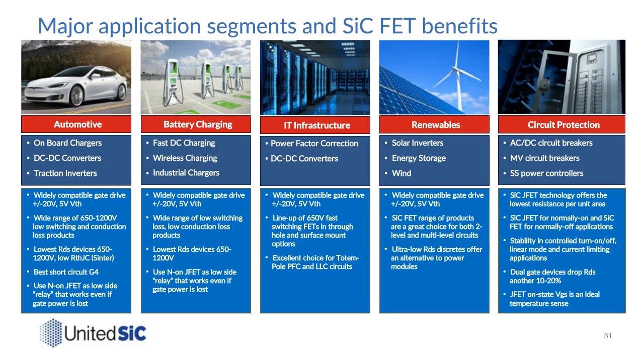This has a 5-volt threshold, so your drive can be 0 to 12, but you can also use other drives if you're looking for compatibility. In liquid-cooled types of applications, like in the automotive segment, you want devices with low thermal resistance. Now, our chips are pretty small because we have an advantage in what kind of RDS-on we can produce for a given chip size. So the thermal aspect of that can be overcome by the fact that we use sintering technology that delivers a pretty low thermal resistance from junction to case.